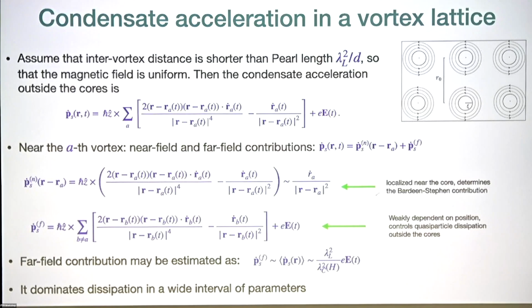And what we need then is to understand how condensate acceleration depends on the coordinates in this state. So I want to be in the regime where the distance between the vortices is shorter than the Pearl length. Then the change in the magnetic field due to screening currents is irrelevant, and we can assume that the magnetic field is uniform, and therefore this superfluid velocity arises because of the transport current and because of the vorticity of each vortex. So then the condensate acceleration arises because vortices are displaced, and this is described by this sum. This is the acceleration caused by the vortex velocities, and also the uniform microwave field.